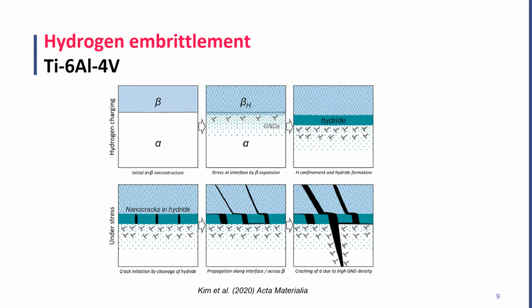Here we can see a nice scheme of how the formation of hydrides takes place and promotes cracking in an alpha-beta alloy. When hydrogen enters, beta phase has a much higher solubility and diffusivity, so hydrogen atoms tend to accumulate in beta grains. However, due to the different strain dilatation and solid solubility, stresses are developed in the interface, leading to the formation of geometrically necessary dislocations and also hydrides. After that, due to the high amount of hydrides and dislocations, cracks nucleate and propagate.